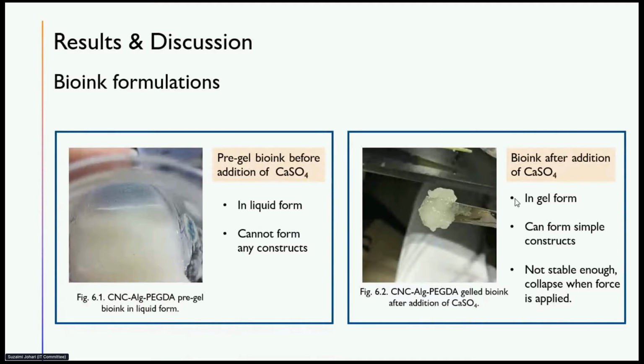So the pre-gel bioink is the picture on the left. It's in liquid form, and at this state, they are unable to form any constructs because of the very low viscosity. Upon addition of the calcium sulfate, which is the picture on the right, they form gel, and then they can form simple constructs. At this state, they are single network bioinks. So although they are able to form simple constructs, they are still not stable because when the height of the constructs increase, they will still collapse, or when force is applied, they will also collapse.